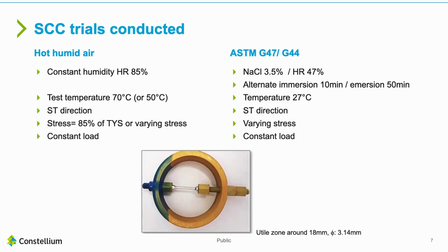The specimens are around 3 millimeters in diameter. They are stressed in the short transverse direction, that is to say the thickness of the plate. And the stress is 85% of the TYS. And we also conducted trials with varying stress, and this is done at constant load.